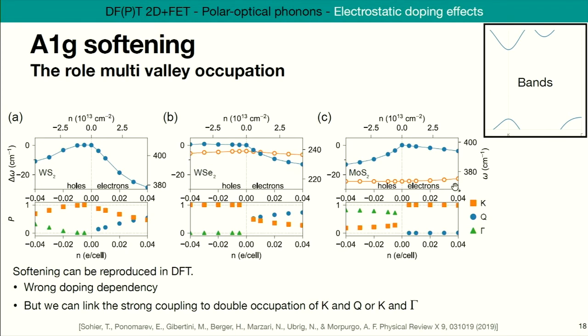So here we need to go back to the band structure, which looks something like this, and there are two valleys, so two minima in the conduction band and two maxima in the valence band. And so there are two valleys. And we saw that when only one valley is occupied, you have no softening. And when two valleys are occupied, you have this softening. And so this is what is plotted here. This is the relative occupation of each valley. When it's zero and one, there's no softening. When they're both occupied, you get some softening. OK, so double valley occupation gives strong coupling, gives softening.